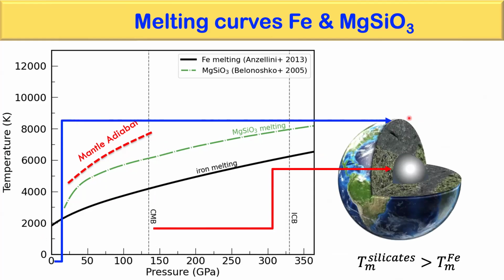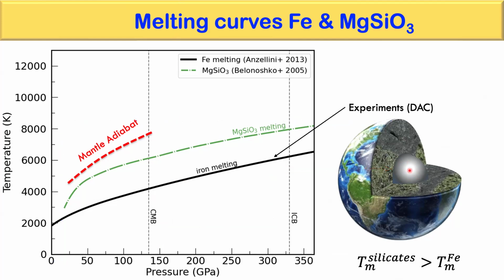and that the core mantle boundary pressure highlighted in this vertical line is where the mantle and the core meet, right? So we're interested in what happens at a certain pressure, which means we're interested in what happens at a certain region of the planet. So many experiments, like the shock experiments I showed you, and others from diamond anvil cell experiments, constrain this melting line at high pressures. They have to reach those high pressures and observe melting and crystallization.